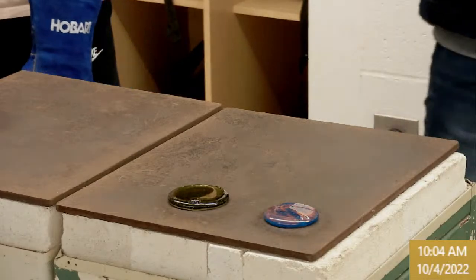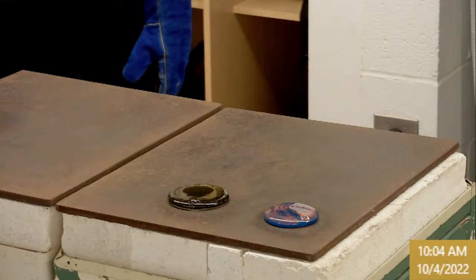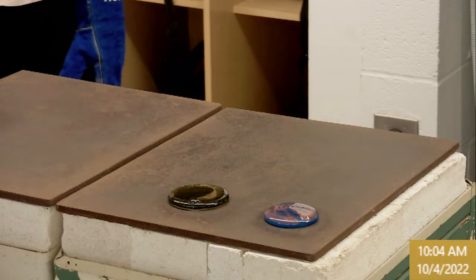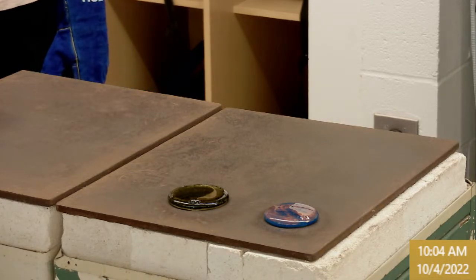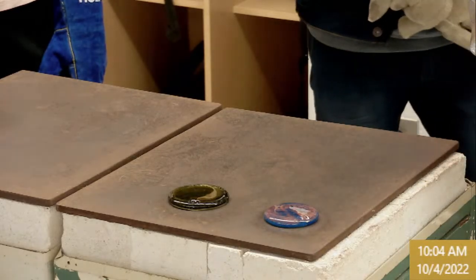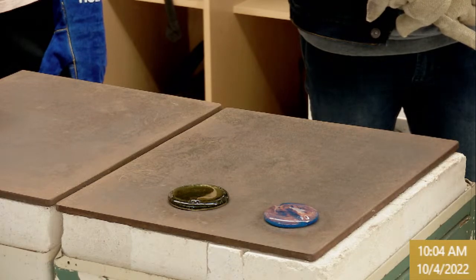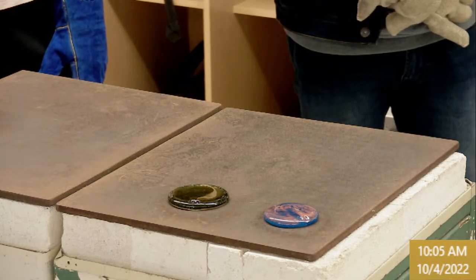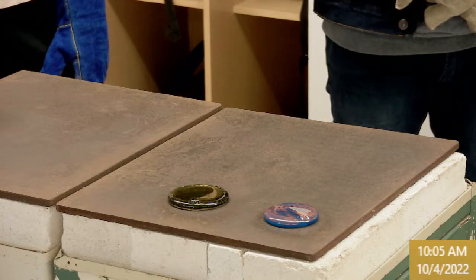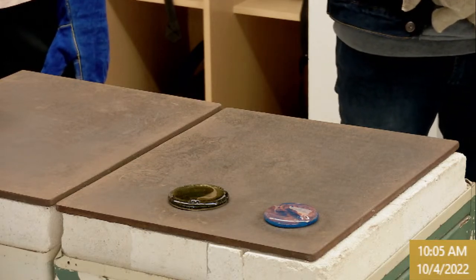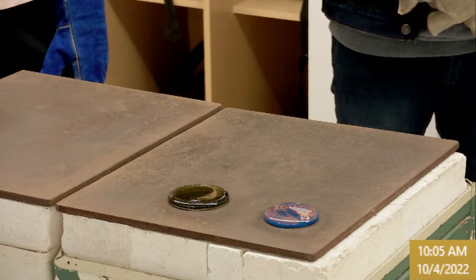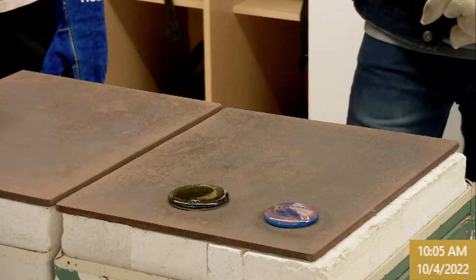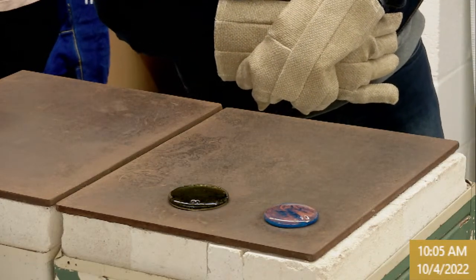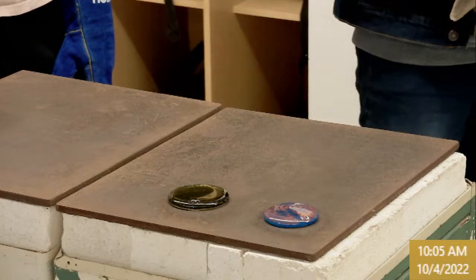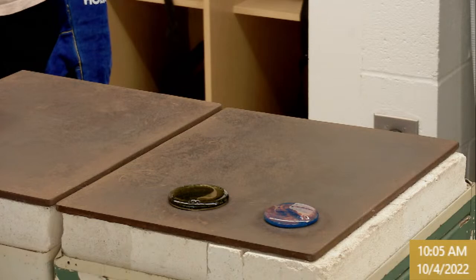All right, so next up is C2. And that cobalt, it's not looking terribly blue at the moment. It's looking more green. Yeah, so I'm wondering if it's the iron from that sand and the low cobalt, because that's not the typical iron color and it's not the typical cobalt color. I think we're piggybacking the native impurity of the iron plus cobalt. That's actually kind of unexpected. So anyway, C2, that's Mason sand, so that's a fairly high impurity sand. They're like little pebbles, dark pebbles in that one.